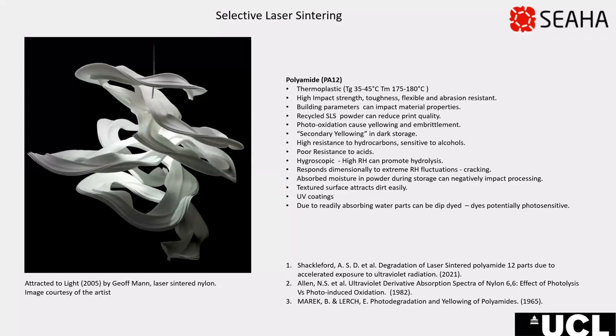Chemical degradation studies into polyamide have mainly been for nylon in the textile industry. Polyamides are known to undergo photo-oxidative degradation, becoming yellow and more brittle. Yellowing in dark storage also occurs, known as post-irradiation or secondary yellowing, due to thermal oxidation reactions continuing on products formed during photo-degradation, particularly in the presence of atmospheric moisture. Polyamide is one of the most hygroscopic plastics, and filaments and SLS-powdered polyamide can absorb up to 10% of its weight in moisture. Extreme fluctuations in relative humidity can lead to cracks, and high relative humidity can also promote hydrolysis, a reaction by which amide bonds break to produce acids and other products.